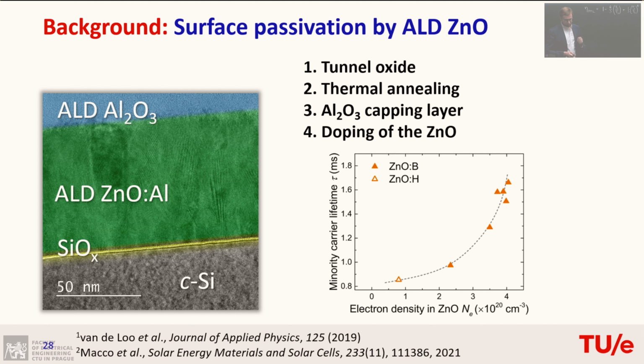And also doping is important. So if you look at the measured minority carrier lifetime here, if you take some intrinsic material, which is in this case marked as hydrogen doped zinc oxide, because we always have hydrogen, but if you then also intentionally dope it with boron, you see that now we have a dopant in our material, meaning you can also benefit a little bit of the screening provided by your dopants, or the field effect passivation, if you like. And you see that now my lifetime is increasing actually as a function of the electron density or just the boron doping level.